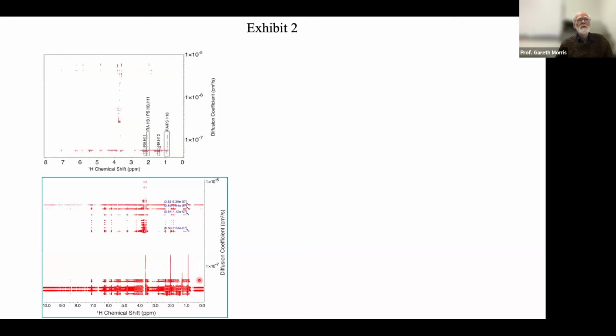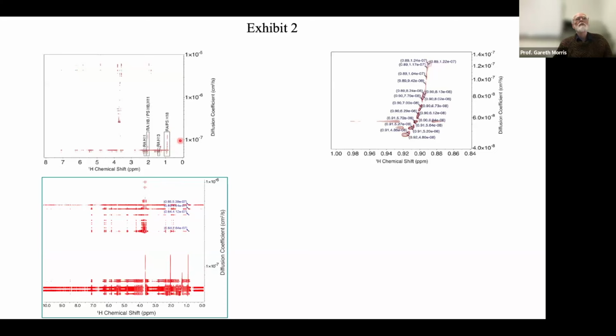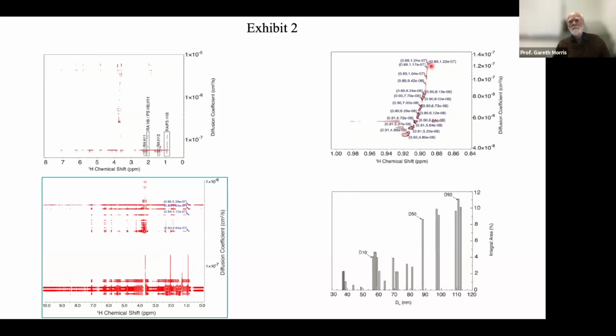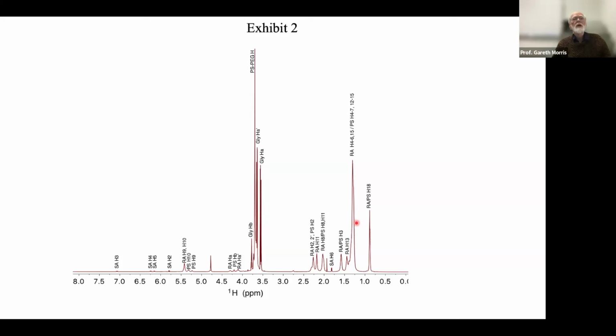Unfortunately, it gets worse. Here's an expansion of the methyl group. And what we see here is that the software has identified a whole series of resolved peaks with different diffusion coefficients, which have then been attributed to different droplet sizes. But if we go back to the raw spectrum, we see that there are no resolved peaks here. Those little segments of signal have all been carved out by the software, trying to be helpful, but leading us